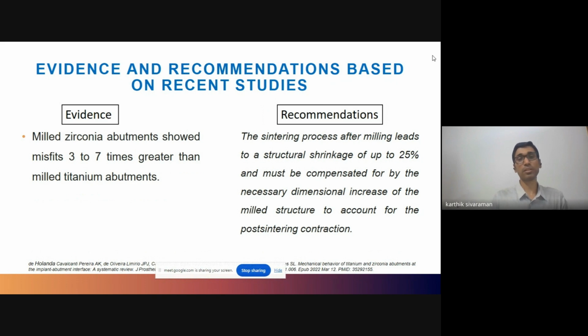The other important evidence is that milled zirconia abutments showed 3 to 7 times greater misfit than milled titanium abutments. And what is the reason? Subsequent to milling, it's subjected to sintering, and this sintering process results in shrinkage up to 25%. So the recommendation is that the necessary dimensional increase of the milled structure should be done during the planning so that it can account for the shrinkage post sintering. So these two sets of points are equally important when we consider integrating the zirconia abutment with an existing titanium implant.